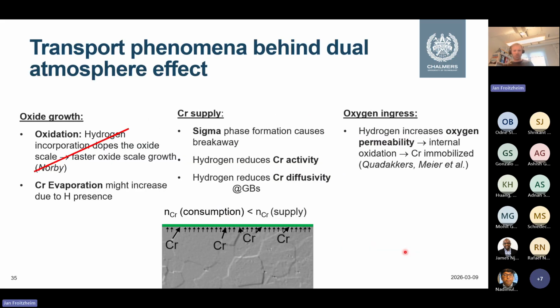Then the question is, what is going on here? From a mechanistic point of view, you can make up all kinds of different hypotheses. This is basically the one mostly found in the literature: that hydrogen is incorporated in the oxide scale, and the oxide scale grows faster. This is clearly disproven, because whenever the oxide scale is protective, the oxide scale thicknesses are pretty similar, if not the other way around. So you can't compare a thin chromium scale to a thick iron oxide scale and say it's growing faster.